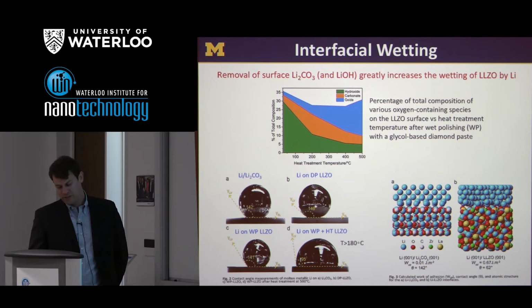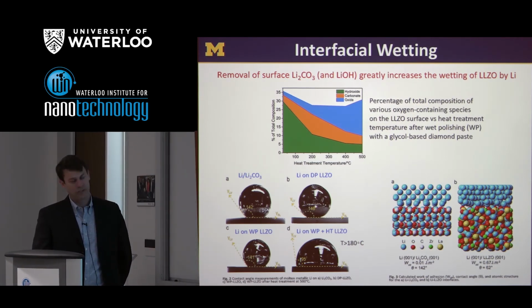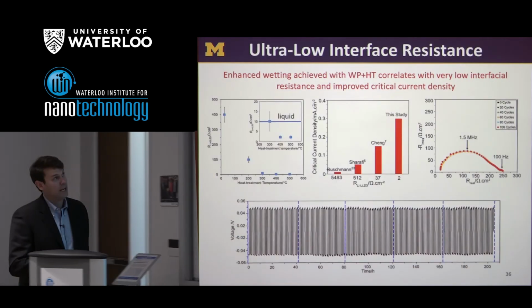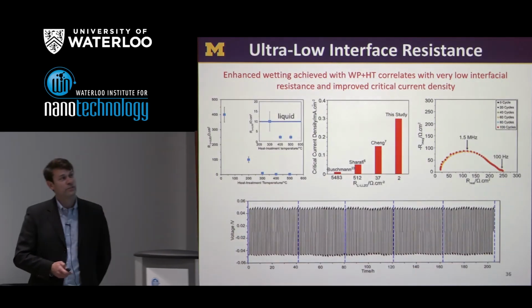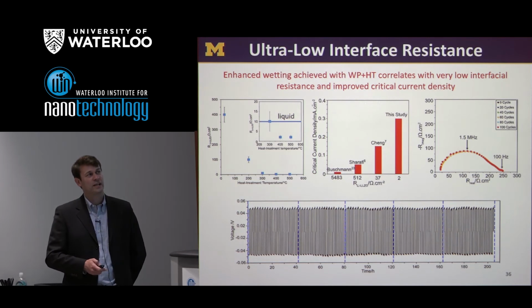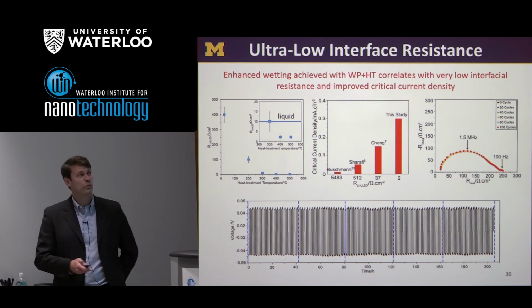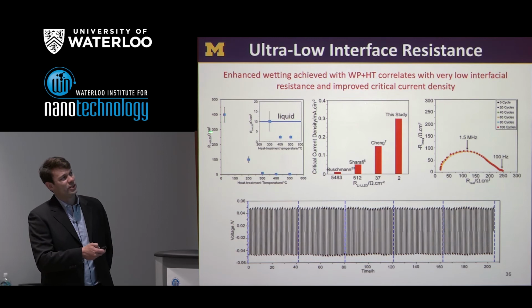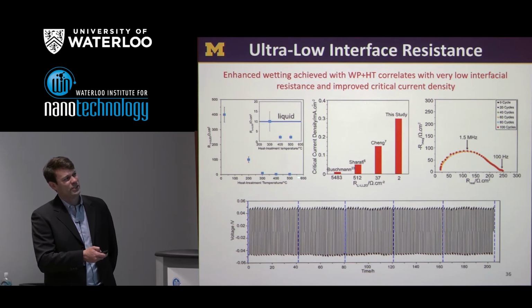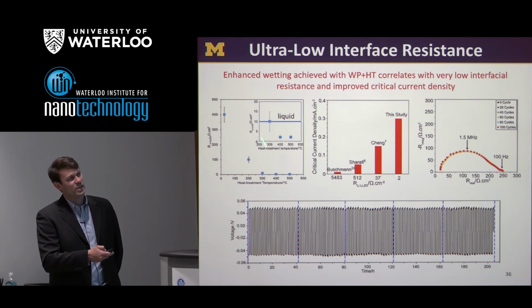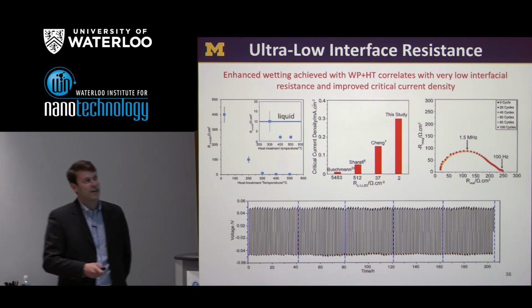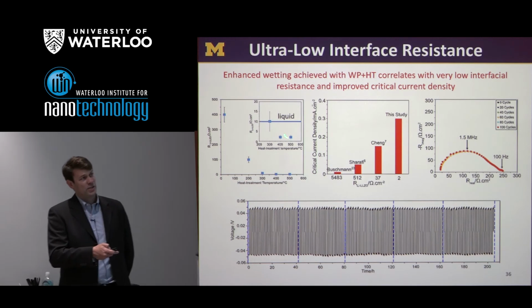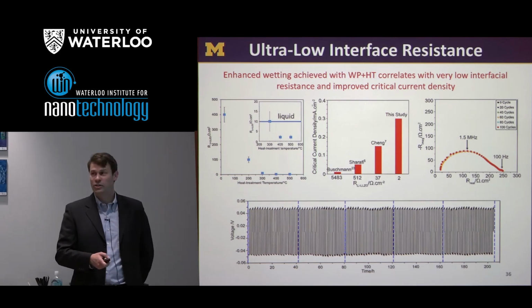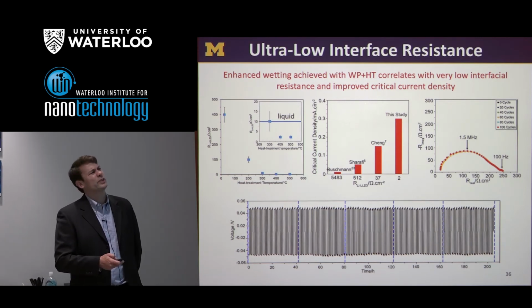So we can increase the wetting, we can reduce the amount of these surface contaminants, and the effect is that the interfacial resistance goes way down and the critical current density goes way up. Here's an example of that interfacial resistance as a function of heat treatment temperature, with a zoom in at the higher temperatures. I've drawn a line here to represent a nominal value for a liquid electrolyte. Here you can see the interfacial resistance actually below that of a liquid electrolyte. And that also raises the critical current density.